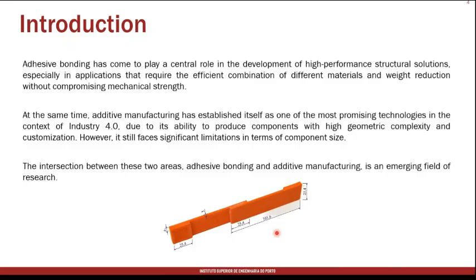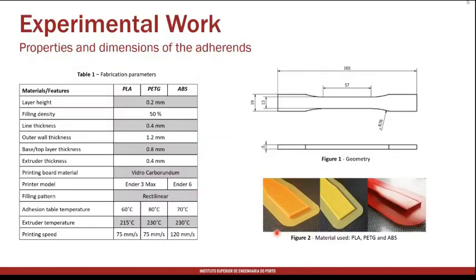And one of the solutions which has been studied in this work is to evaluate the adhesive bonding between polymeric joints. Some details on the 3 types of adherends. Here we can see 3 printed dog bone shaped adherends for tensile testing, one for each one of the materials, PLA, PETG, and ABS, and also the parameters that were used in the fabrication of this component.